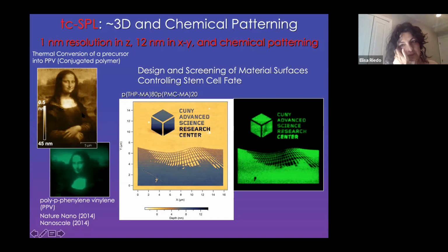In this case, it's a very different type of thermochemical reaction. This is a precursor polymer of PPV. PPV is a conjugated semiconductor polymer, which once the precursor is transformed into PPV, PPV is also fluorescent. It's semiconductor and fluorescent. So what it shows here is that the image is showing some fluorescence, but it also shows a 3D patterning, because when the precursor is transforming into PPV, there is also a shrinking process. So you can also change the topography by looking at the, sorry, not a shrinking, a swelling process.